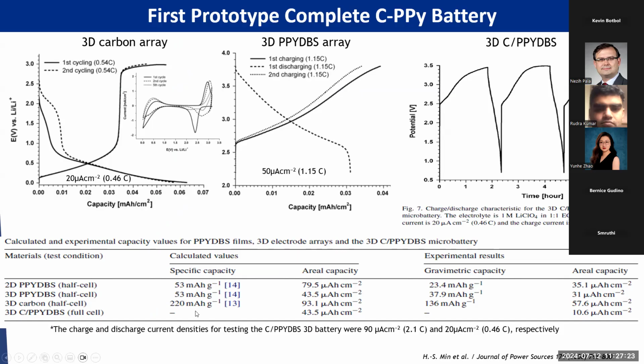For the anode side, the glass carbon can deliver okay performance, let's say 220 milliampere hour per gram. That's a specific capacity. And if you look at the area capacity, we can deliver 93.1 microampere hour per centimeter square. Compared to graphite, it's only, let's say, 2/3 of the performance, because we're using hard glass carbon and it's amorphous carbon. So the performance is not as good as graphite, but for demonstration of our first prototype, it's good enough. So we still look at the half cell performance here for the 3D polypyrrole.